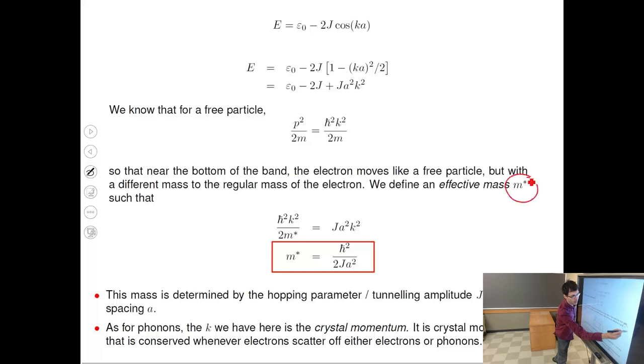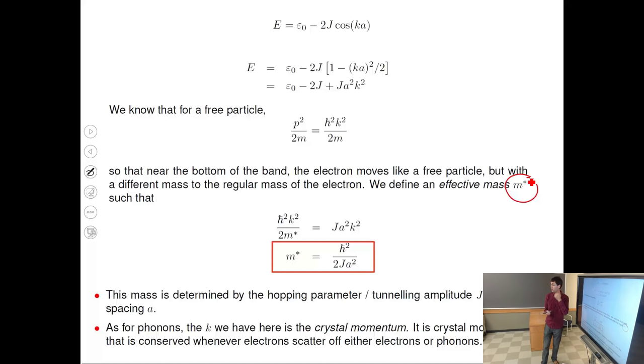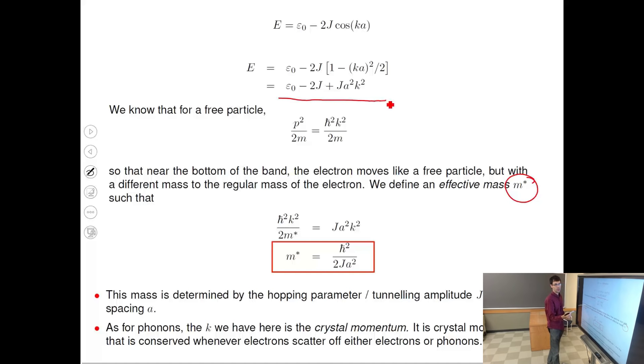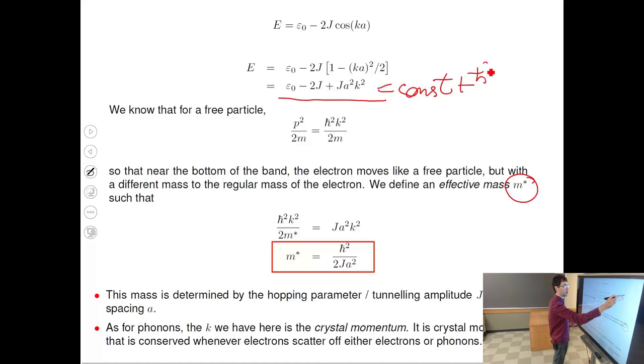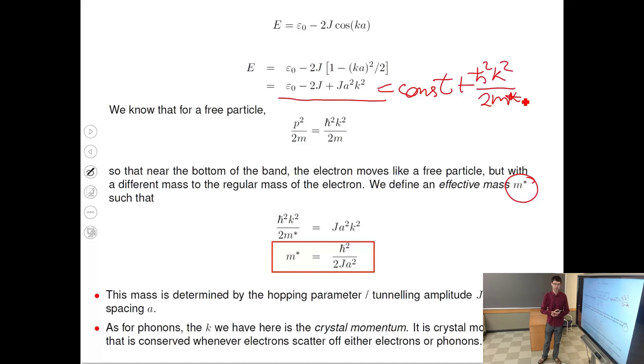This leads to the concept of effective mass M*. We match the dispersion to ħ²k²/(2M*) plus a constant, giving M* = ħ²/(2ja²). Effective mass plays the role of mass in the dispersion relation: close to k=0 the cosine behaves parabolically, and M* captures that curvature. It depends on j and a — not on ε₀, which plays a role analogous to rest mass energy mc².